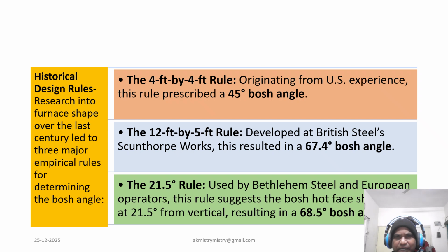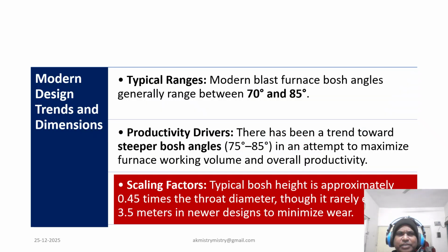In terms of scaling, a typical Bosh height is approximately 0.45 times the throat diameter. However, to minimize excessive wear, modern designs rarely allow the Bosh height to exceed 3.5 meters. The impact on wear is also very important. However, steeper is not always better.